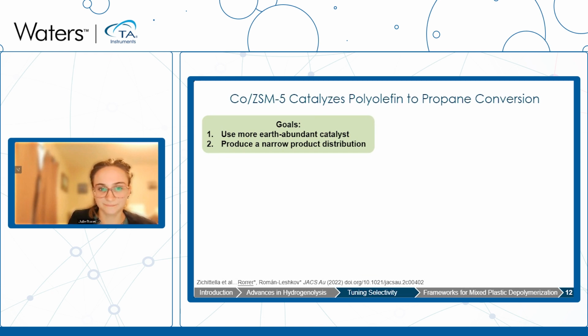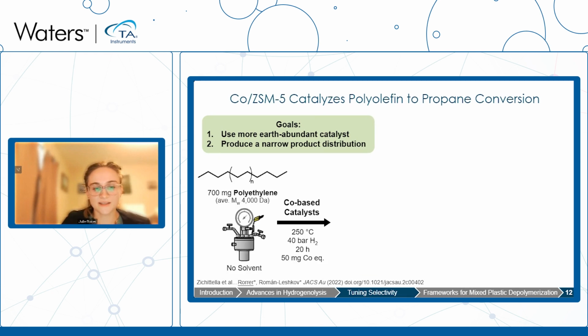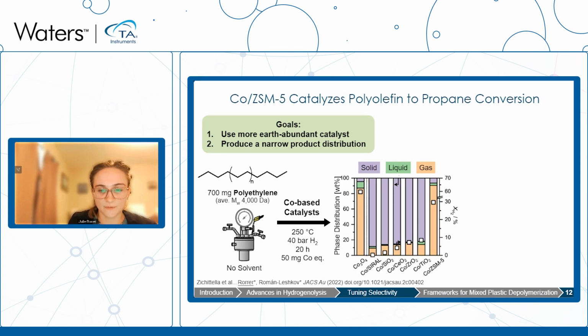And so we wanted to think about what type of catalyst could catalyze this reaction, and we identified cobalt-based catalysts as very interesting because these have been employed before for cleaving apart carbon-carbon bonds in the biomass and lignin depolymerization literature. And so we screened a variety of different cobalt catalysts on different supports. And what I'm going to show you here is that 2 of these catalysts stood out. One is bulk cobalt oxide, and the other is cobalt supported on a different zeolite called ZSM5.